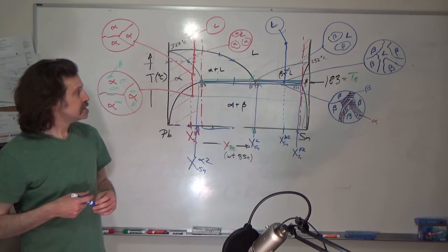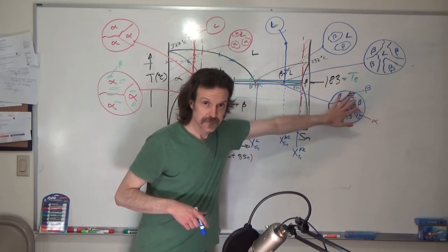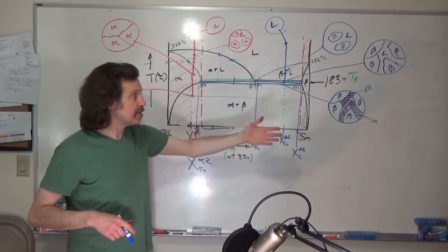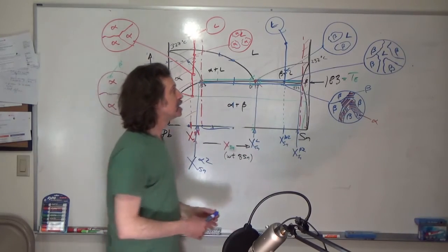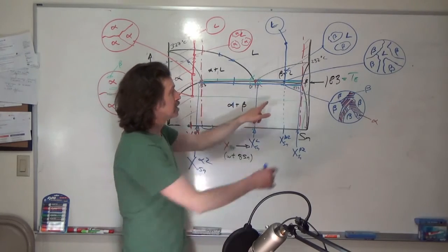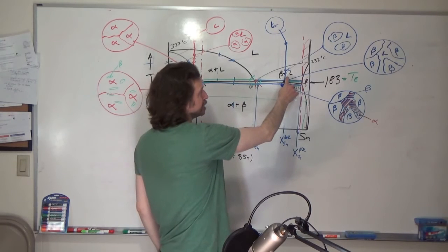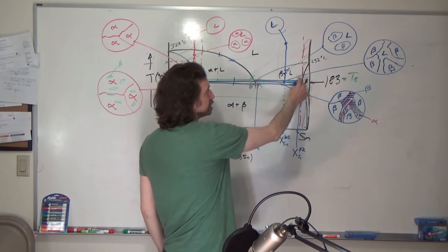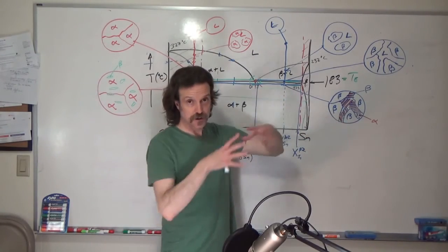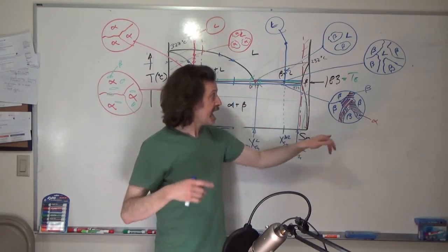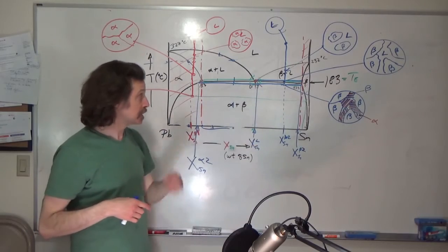and the fraction of the volume that is given by the eutectic microstructure is really determined by where we are in here, right? So for example, if we move more to the right, we're going to have more of the large beta crystals and a smaller amount of the eutectic microstructure.